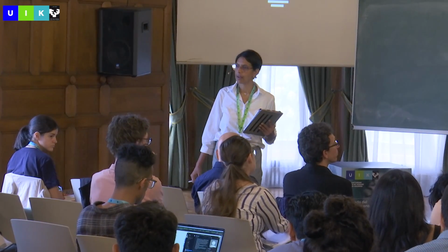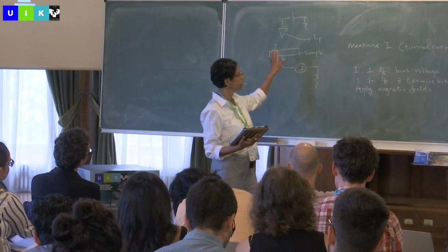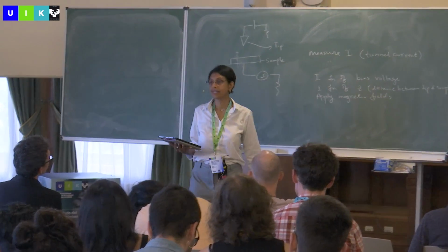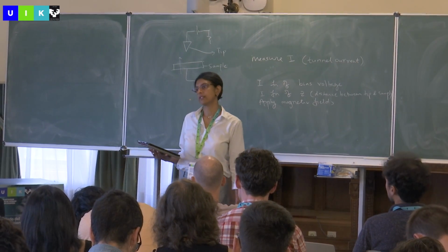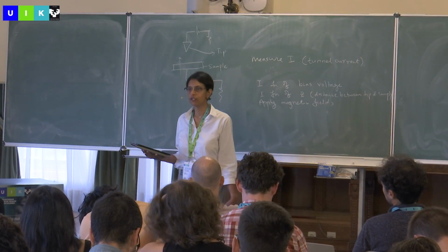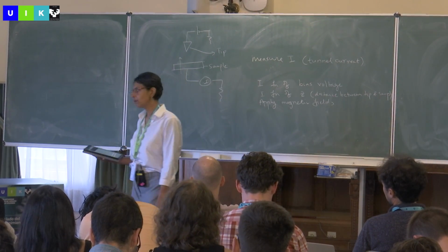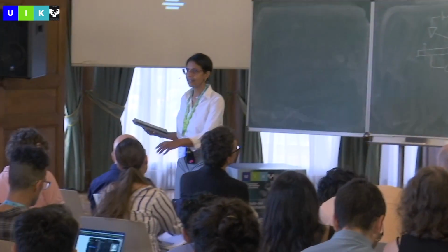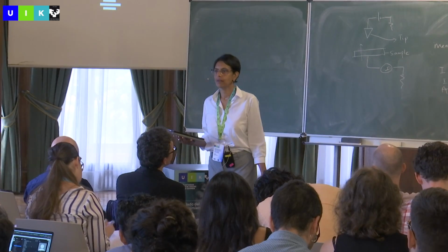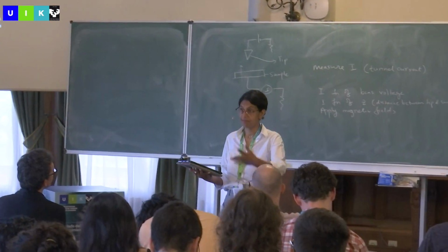What does it mean for the experiment? If you move a magnetized thing, you should induce electric fields, so do you have to wait all the time after? Yeah, this is a good question. I should have mentioned this. Think of STM as a quasi-static probe. We actually move very slowly on the scale of the equilibrium time of electrons, which is femtoseconds. We just take our own sweet time, and we move on millisecond time scales, raster the tip, I mean. So everything we do is quasi-static, static if you wish.